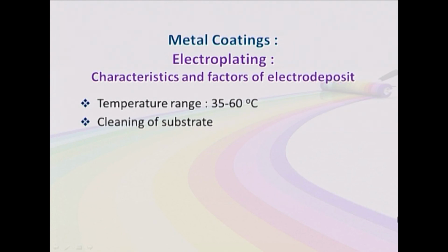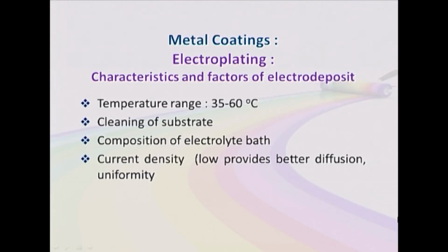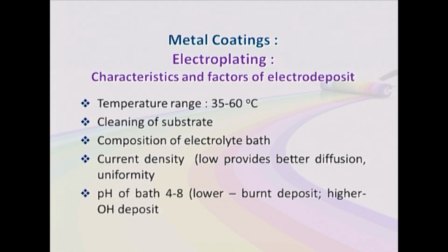Cleaning of substrate, this is very important. If the surface is not properly cleaned, then the coating will not be proper. Composition of electrolyte bath. Many conditions, types of the salts we are choosing, their concentration, affect the electroplating. Current density. As we know, low current density provides better diffusion and we get a uniform layer. pH of the bath. It should not be too high or very low. At lower pH, meaning acidic conditions, burnt deposit is obtained, and at a higher pH hydroxide ions get deposited on the surface.